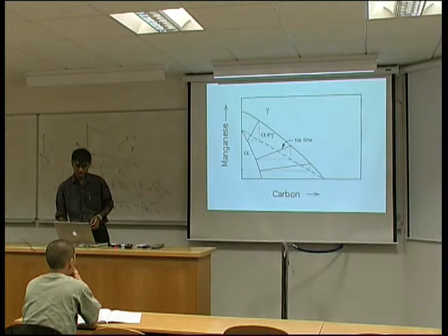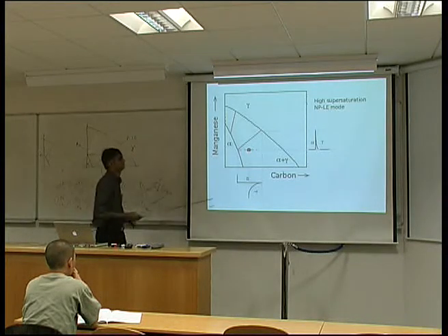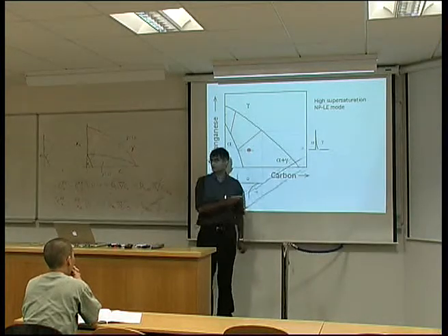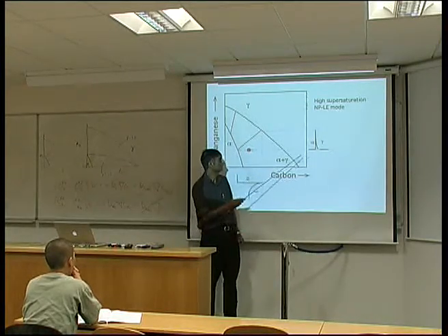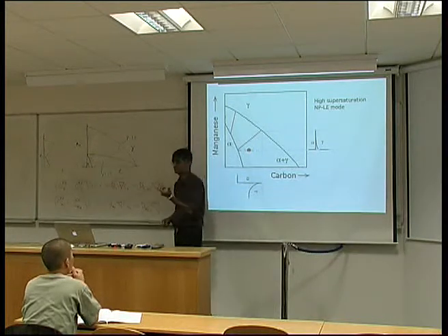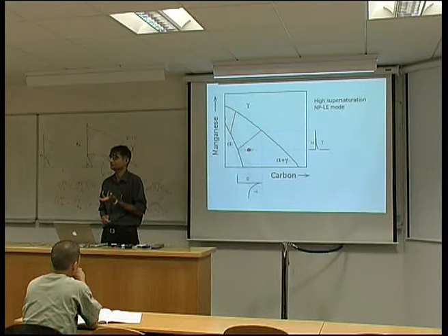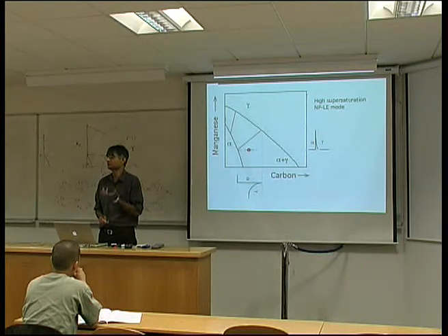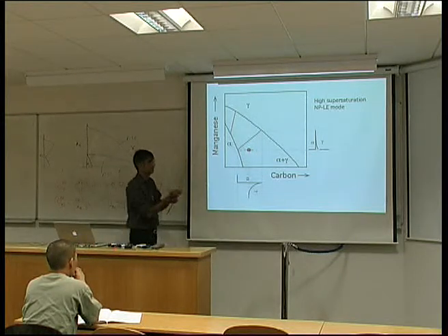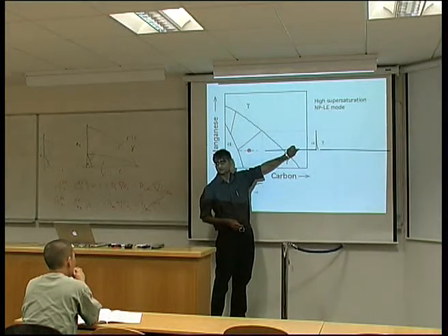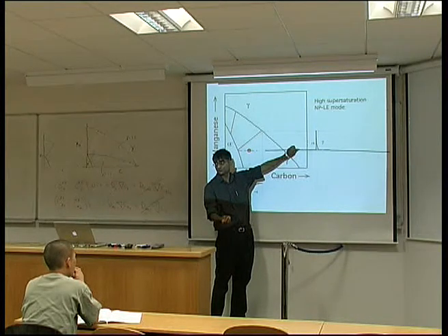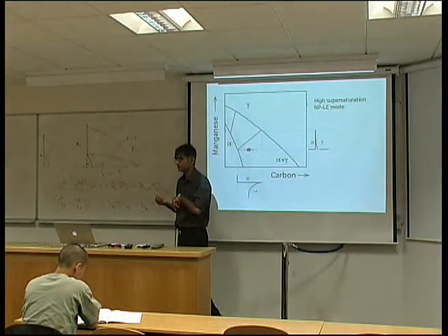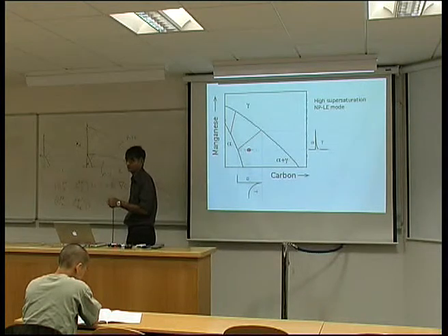So, if we look at this concentration profile here, it's very, very steep. Eventually, this diffusion distance becomes less than an interatomic spacing, which means it doesn't make physical sense. And manganese simply stops diffusing. But carbon can continue partitioning between the two phases. So we've lost equilibrium when that happens. This profile becomes completely flat when we go to a low enough temperature where the diffusion of manganese becomes too sluggish. So we can no longer talk about equilibrium, we can no longer use an equilibrium phase diagram.